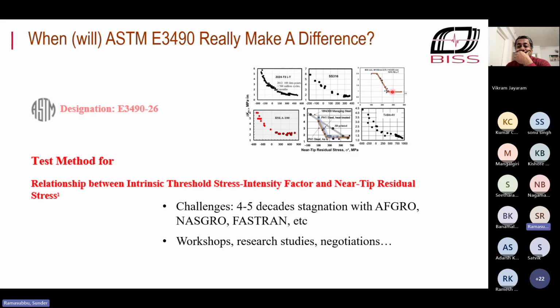Whereas here you're sensitive to stress state, but under threshold conditions, for most of the crack front, you actually have a plane strain condition. Therefore, the stress state remains the same. Remember also that you determine the stress strain curve, which is an important input for this property. The cyclic stress strain curve is obtained on smooth specimens, which see plane stress conditions. But that doesn't matter because it's a mistake that is made at the system level. Therefore, it reproduces in the modeling, and that's how you get away with it. So you don't have to have the stress strain properties in for the plane strain condition.